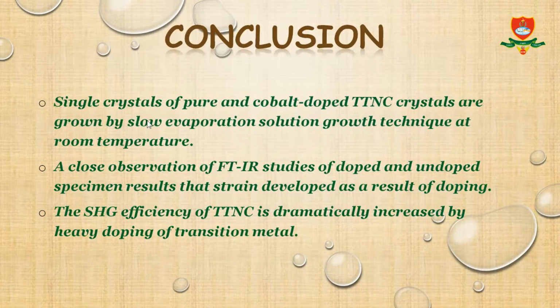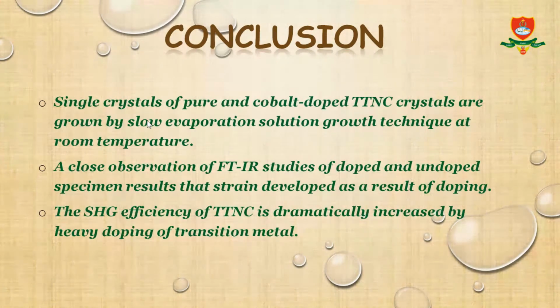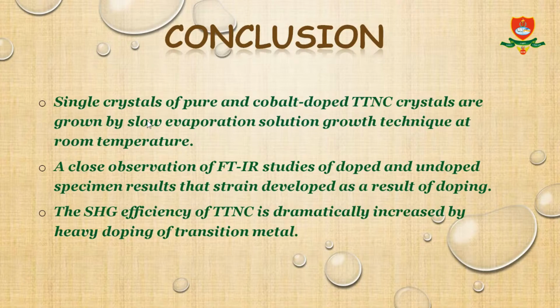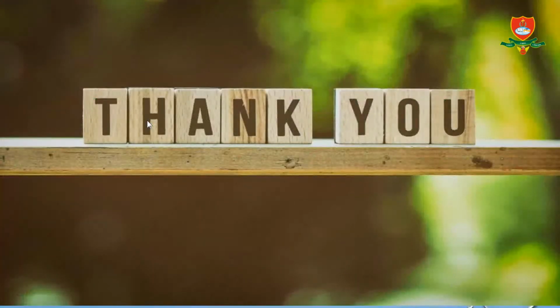Conclusion. Single crystals of pure and cobalt doped TTNC were grown by the slow evaporation solution growth technique at room temperature. A close observation of the FTIR spectra of doped and undoped specimens shows the strain developed as a result of doping. The SHG efficiency of TTNC is dramatically increased by heavy doping of a transition metal. Thank you.